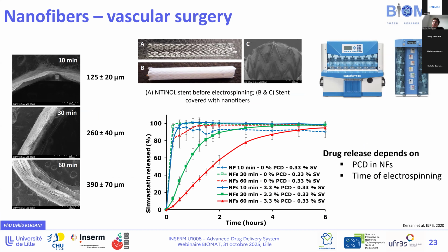In this case, it's for vascular, so we adapt the model of release. We use flow-through cells, so it's a dynamic, closed system. We can put the stent inside the machine, coat agar gels around the stent, and evaluate the profile of release inside the stent online.